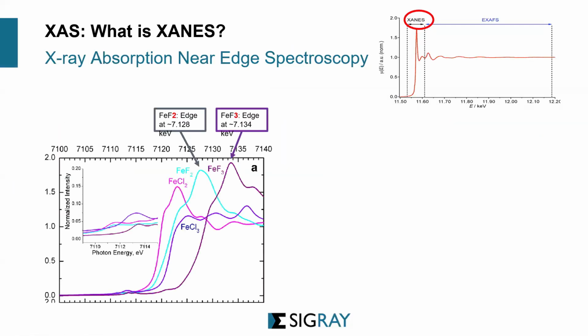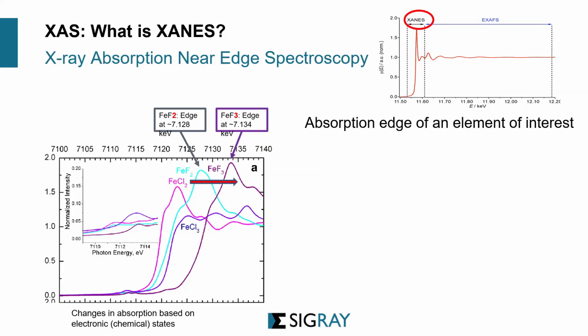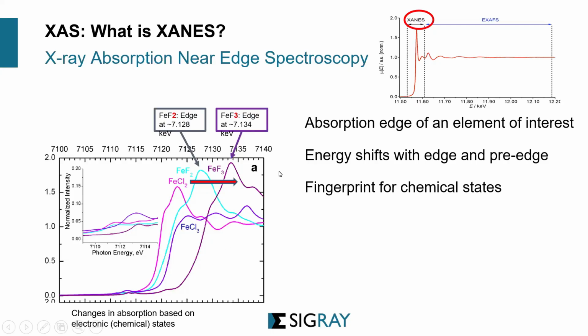Let's take a deeper dive into XANES. Let's say I have a set of chemicals based on iron: iron 2 chloride and iron 3 chloride, iron 2 fluoride and iron 3 fluoride. We run an X-ray absorption on these materials. You find that the absorption edge of the element of interest shifts according to its chemistry. The higher the oxidation number, like iron 2 to iron 3, the more the shift is towards the right. The same goes for iron 2 chloride to iron 3 chloride. Every one of them has a unique fingerprint, just like FTIR. You have a unique fingerprint in absorption spectroscopy.